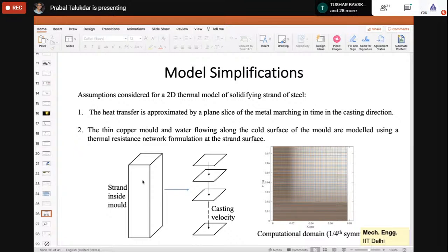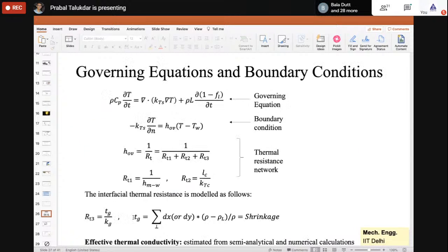If you can calculate all these resistances, based on your resistance network analogy, you can calculate the total resistance. Once you know the total resistance, from that you can calculate the overall heat transfer coefficient, and that overall heat transfer coefficient can be considered as a boundary condition, and you can solve only the billet problem with that boundary condition. Mold will not come into the picture here, right? You don't need any interfacial heat flux condition, because now your boundary is actually a cooling boundary, and you have a convective boundary condition, right? So there is no heat flux required now. Only the overall heat transfer coefficient, for which you have three terms.